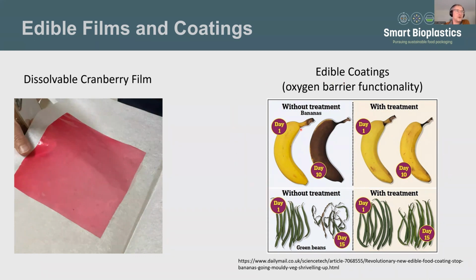It's quite impressive if you coat, for example, bananas in there. After 10 days, we have our normal brown banana that nobody likes to touch. But if you coat the banana with, say, these edible films, you see that there's hardly any oxidation happening after 10 days. So this would be very much still usable and attractive for any consumer to eat. The same, for example, with green beans. Without treatment and coating, after 15 days, they look very shriveled and unappetizing. Whereas if those are coated, they pretty much look very usable and edible still.